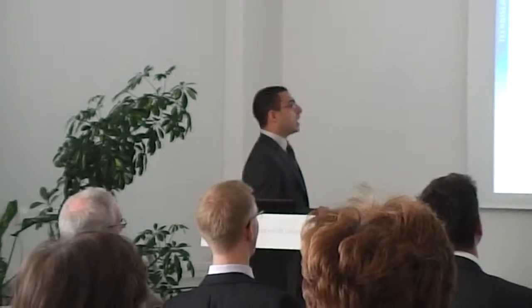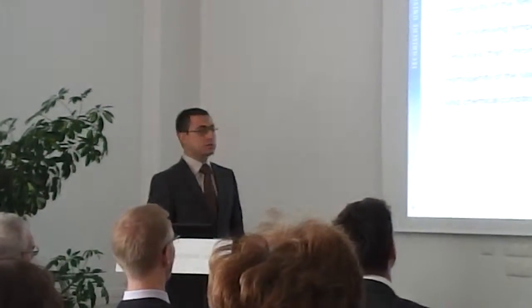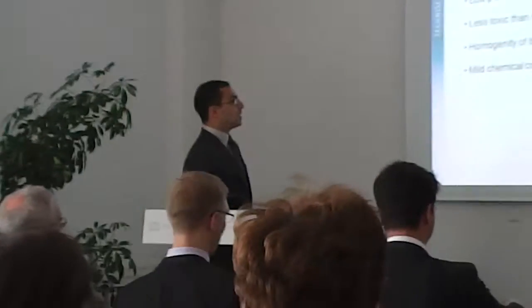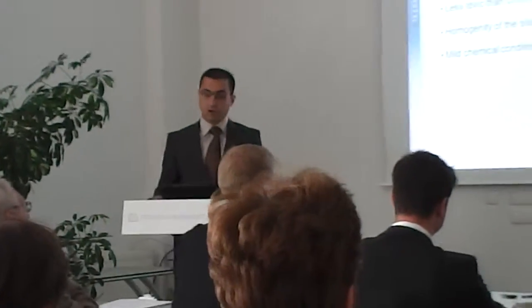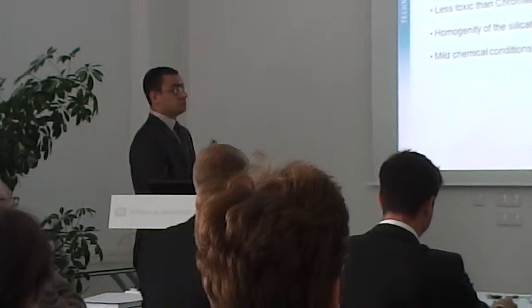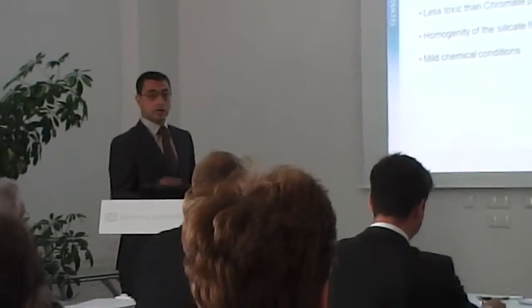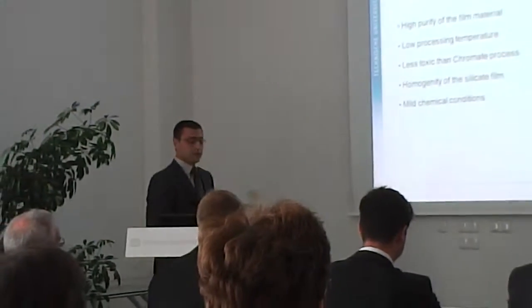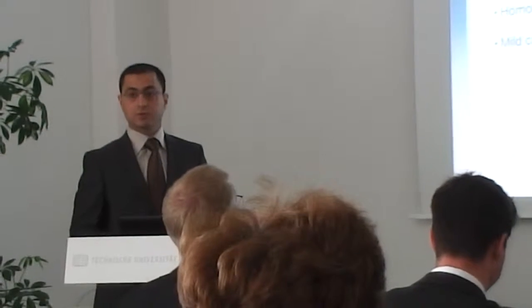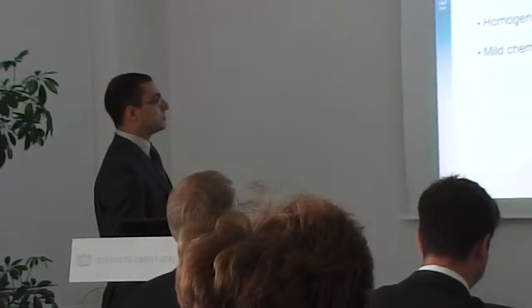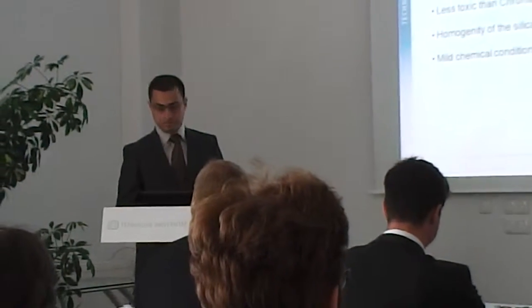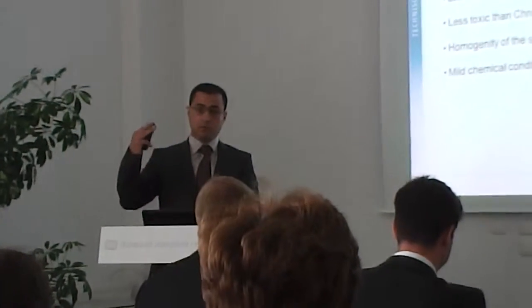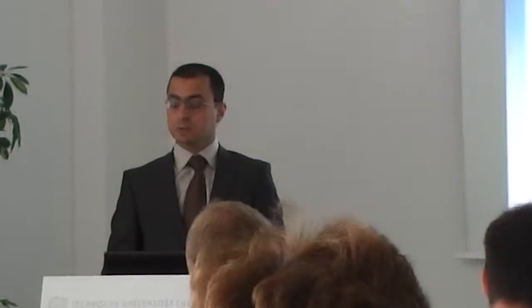Disadvantages. The high cost of the starting materials. Volatile organic compounds are needed to achieve the homogeneity of the sol. These materials are toxic, like methanol, flammable, and it also has a cost. Cracks are usually formed in the silicate film during the heat treatment, and these cracks are the main reason for corrosion. Also, only thin films can be applied, thickness maximum 3 micrometer. When the film thickness is 4 or 5 micrometer, that means cracks will occur.